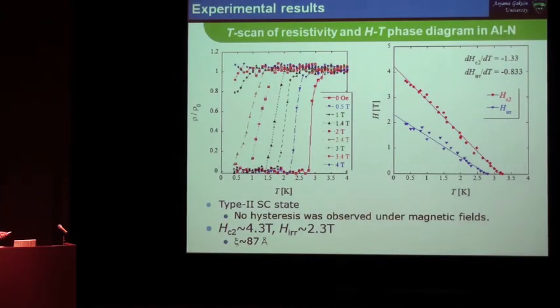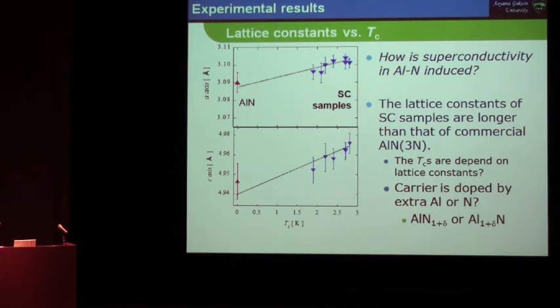This is a T-scan of resistivity and phase diagram in aluminum nitride. To carefully conclude that this is not an aluminum material, we compare the stoichiometric aluminum nitride and our superconducting aluminum nitride. It is a very delicate conclusion. However, the lattice constant is clearly different along the A-axis and C-axis.